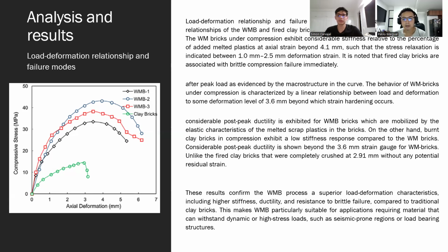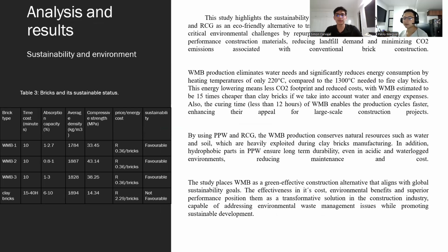The failure modes, the representative load deformation relationships of the WMB and clay bricks under compressive stress are presented. The WM bricks under compression exhibit considerable stiffness relation of the percentage of added plastic at axial strain. With the data of the graphic, these results confirm the WMB possesses superior load deformation characteristics, including stiffness, durability, ductility, and resistance to failure.